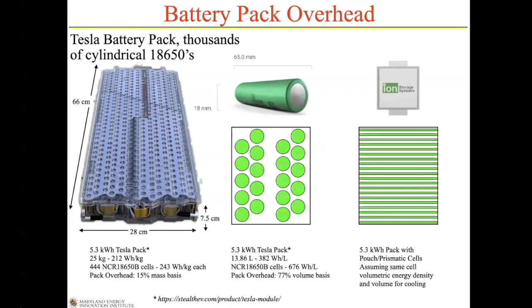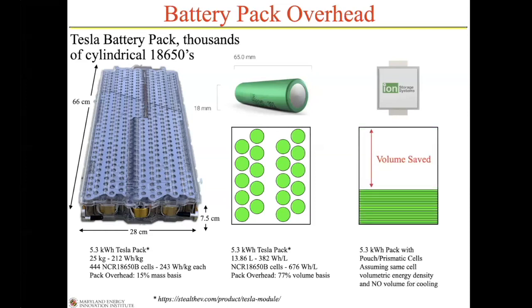And so, what I can do if they're flat like that, I can pack them and have the same spacing. And so this would be this same 5.3 kilowatt hour pack, but now configured with a planar, either a pouch or prismatic cells. And that would allow the same area for cooling for that fluid to flow through between them. Now, if I didn't have to cool them, in fact, I could pack them much more tightly. And now you can see the dramatic reduction in volume of the battery pack relative to what it currently is just by removing that need for cooling to maintain temperature.